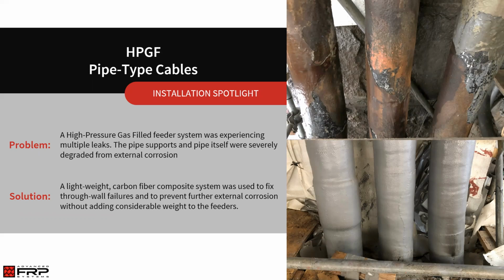With carbon fiber, the low density that I showed you, we were able to add a minimal amount of weight while providing a completely leak-free system, even with numerous through-wall failures. And this was all done on vertical piping and piping with irregular elbows. So we had no issues with the vertical piping, and no issues working on scaffolding or with the elbows.